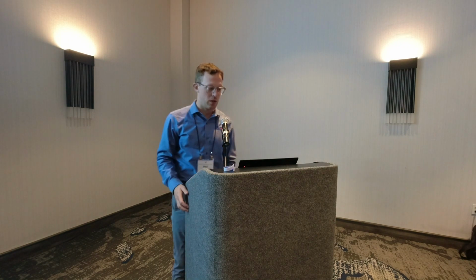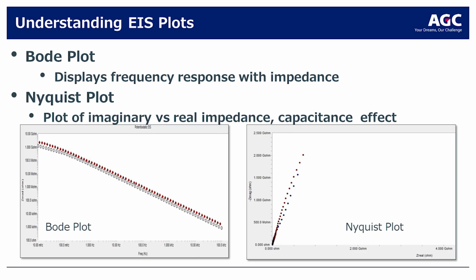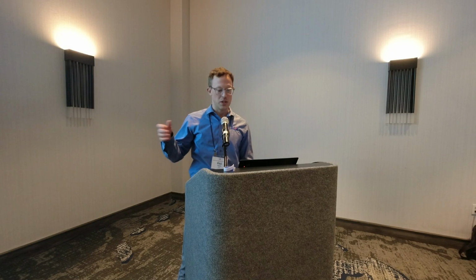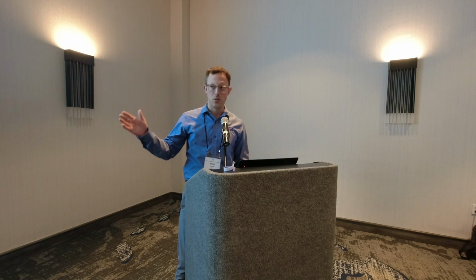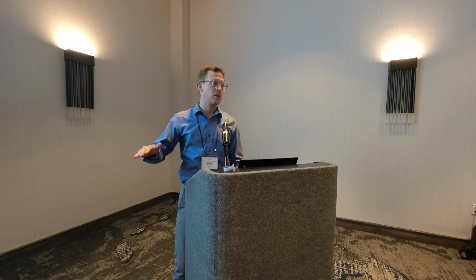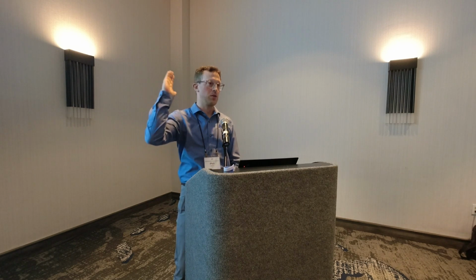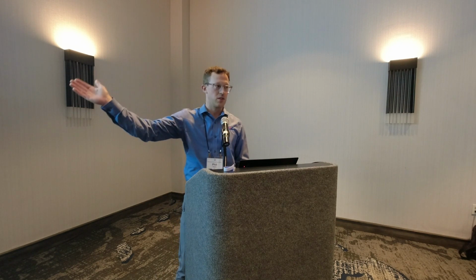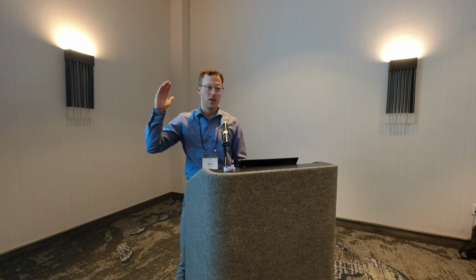So within that, we have the two plots for the EIS testing, where you'll pull out a Bode plot or a Nyquist plot. The Bode plot is you just take a point in time and compare what that frequency is for the impedance, so it just gives you the Hertz number. And with the Nyquist plot, essentially you're looking at that resistance. A perfect corrosion resistance insulator on a Nyquist plot is going to be straight up and down. That's what you want. You want that infinity, that the mathematics, if we're going back to the textbooks, that's what you're looking for.